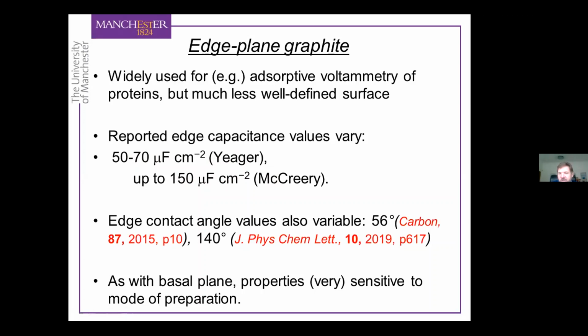Same with the contact angle of water on the edge plane. We only found one literature value, and that was about 56 degrees. Whereas when we tried to measure this ourselves, and this is the paper that our specific ion capacitance data was published in, we got a much higher value. We got the contact angle of about 140 degrees. So basically there's big inconsistencies in the fairly fundamental data of the properties of the edge plane electrode